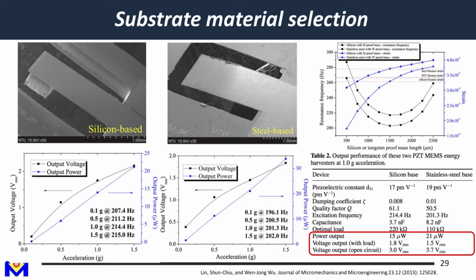For example, for a certain deposition chamber, you can only put certain kinds of material into the chamber. So if you want to change the substrate, you need to consider whether this substrate material is possible in all your processes, including deposition, etching, and also lithography, like double-sided lithography if you want to make a bimorph. Okay, so in the end, I said, well, we try. So we tried stainless steel, and in the end we found it has a lot of advantages.